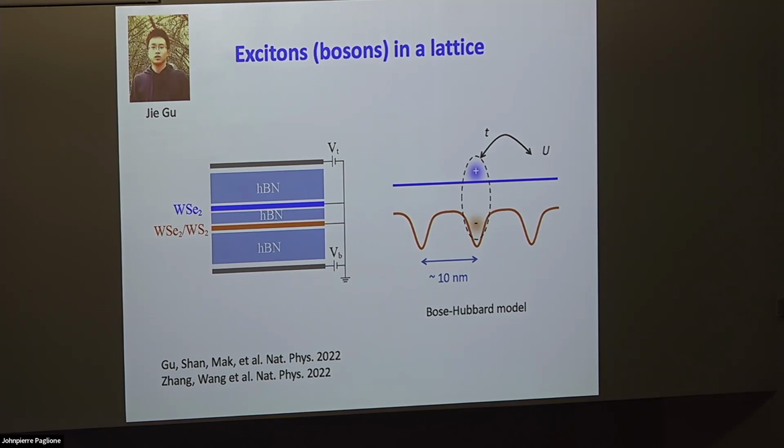So controlling the angle between the two layers precisely must be very challenging for reproducible samples. Yes, actually. How do you control that? Yeah, so that's why we are doing a lot of heterobilayers, because we just need to snap them at 0 degree, close to 0 degree. Then the moiré lattice structure is dominated by the lattice mismatch of the two materials, not by the twist angle.